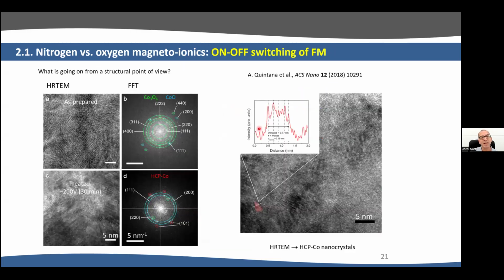But first, let me explain why the cobalt oxide becomes magnetic. As you can imagine, after my introduction, the idea is that when we apply voltage, the oxygen ions may migrate from the film and create some metallic clusters of cobalt, which is magnetic. And this was confirmed by high resolution TEM. You can see here on the panel, the as prepared state is basically a mixture of cobalt tetroxide (Co3O4) and cobalt monoxide, so non-magnetic phases. But after we apply negative voltage for some time, we start seeing these additional spots that correspond to magnetic hexagonal cobalt, and we can even detect where these crystals are.